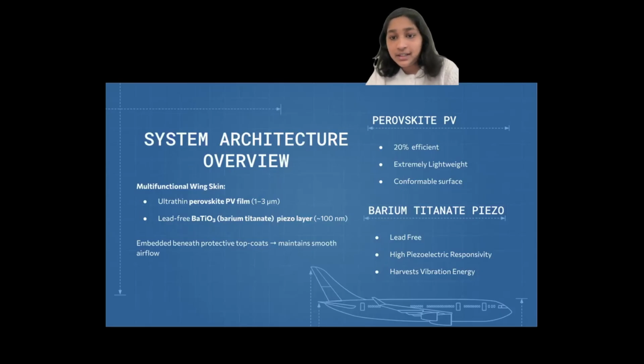The piezoelectric layer uses barium titanate based 100 nanometer films, chosen for being lead free, mechanically stable, and exhibiting strong piezoelectric coupling. At this nanoscale thickness, the piezo layer is essentially a functional coating, capable of converting wing vibrations, which are those tiny rapid oscillations produced as airflow flows over the surface, into electrical charge. For perspective, 100 nanometers is so thin that if the wing was scaled to the height of a skyscraper, the piezo layer would be like adding a single sheet of paper to it. These two materials, one harvesting light and the other harvesting motion, together form a hybrid multifunctional energy harvesting architecture.